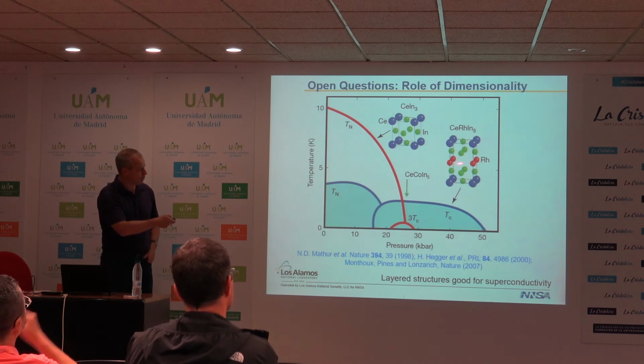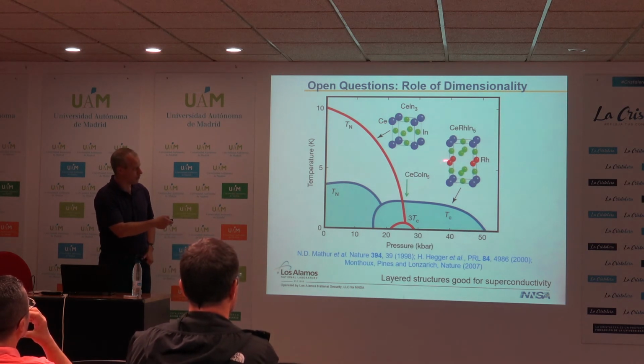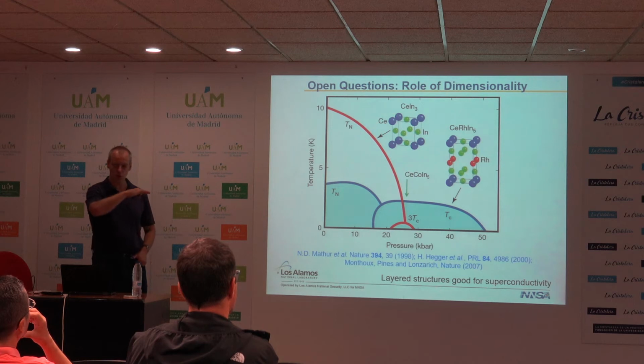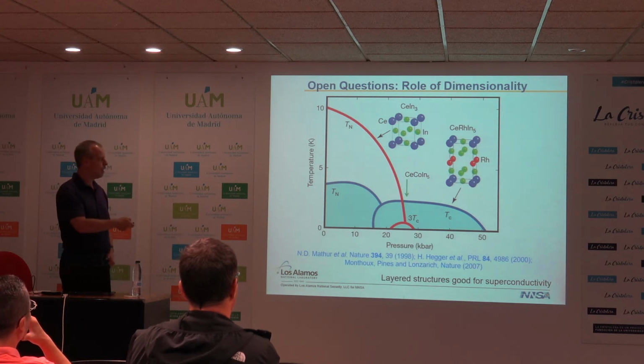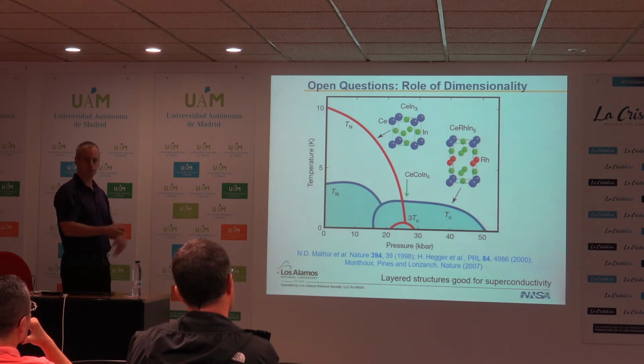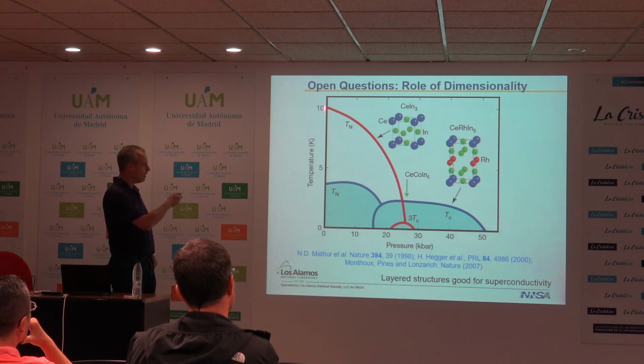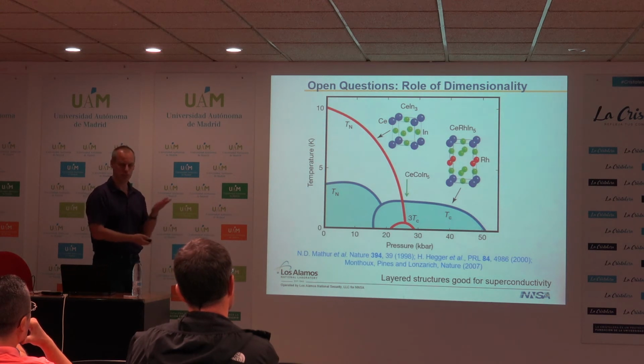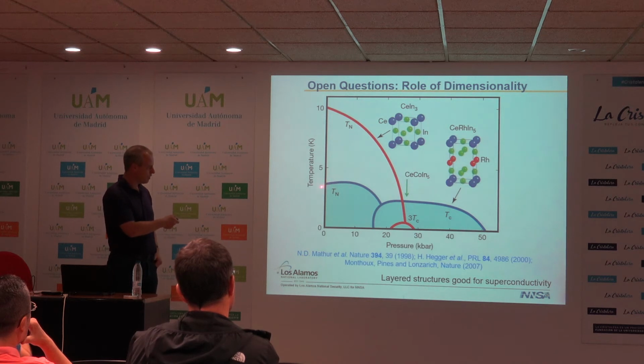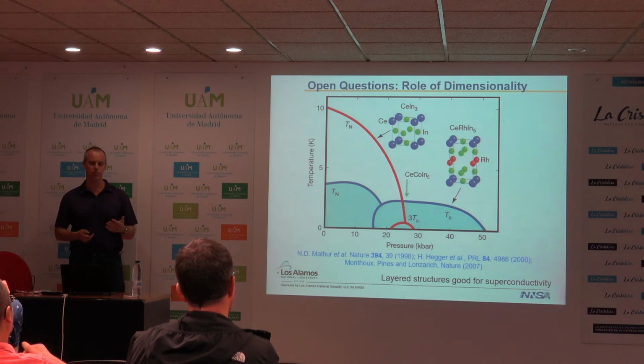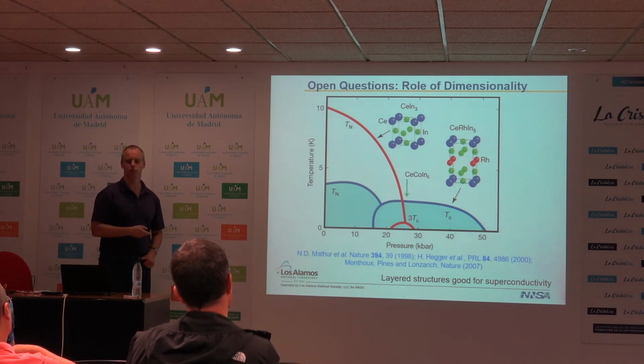What was found out by our group in Los Alamos, and this predates before I even got there, was that you could insert just a layer of rhodium. So just a layer of rhodium atoms between the cerium indium 3, and that forms this so-called 115 structure. So for instance, cerium rhodium indium 5. Because this system is now quasi-two-dimensional, a layered version of cerium indium 3, the magnetism comes down, as you would expect, reducing the dimensionality of the magnetism. And when you apply pressure now, the magnetism is again suppressed with pressure. You get a dome of superconductivity, but the maximum TC is now 2 Kelvin. So we've increased TC by an order of magnitude just by inserting this layer of rhodium.